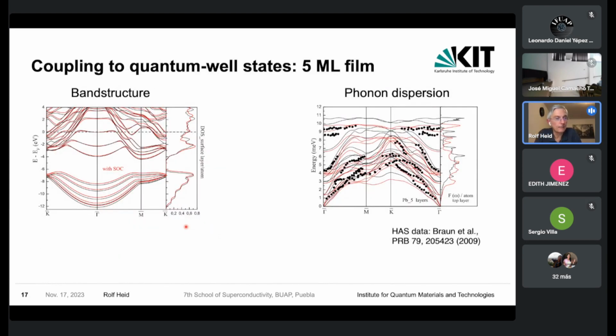Now we have applied this machinery of calculating electronic properties, phonons, and the electron-phonon interaction to these different types of films. And this is now the result for one of these cases, namely for 5 monolayer films. So we have 5 layers of lead stacked on top of each other in a 1-1-1 geometry. On the left-hand side, you see the corresponding electronic band structure. There are two plots on top of each other, a black and a red one, and the red includes the spin-orbit interaction, while the black one is the so-called semi-relativistic calculation without spin-orbit interaction. Here you see that the electronic structure is very similar for these 2 cases.